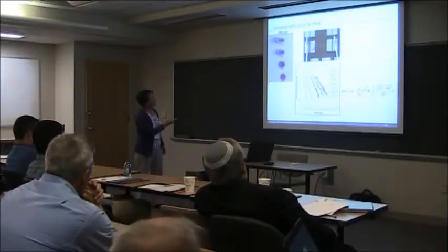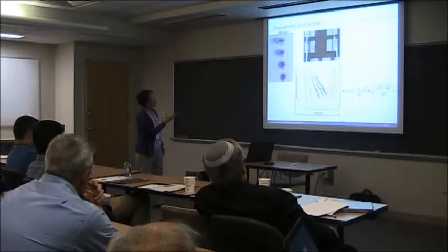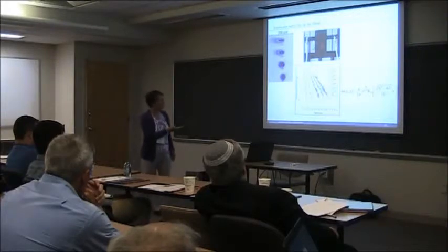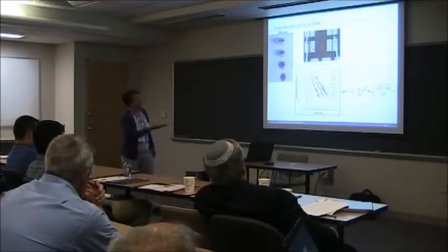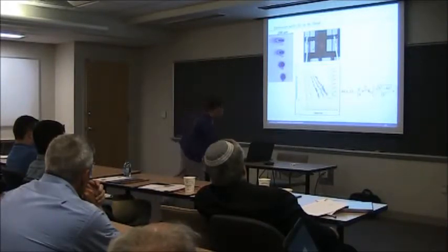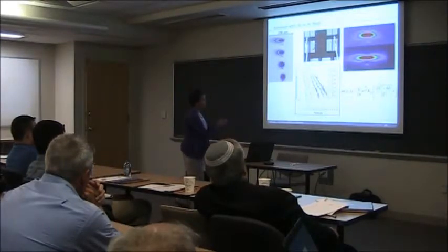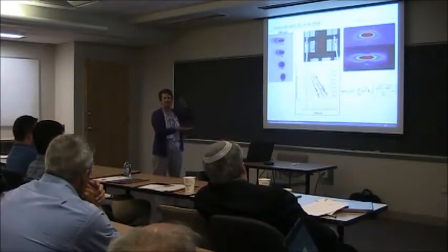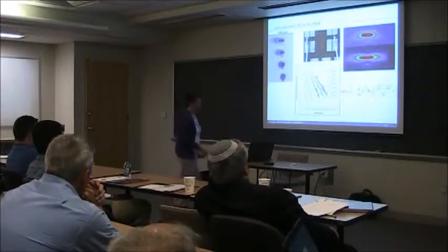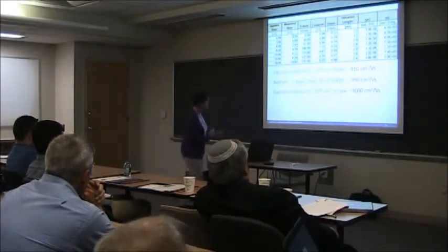Generation point right there, you see the diffusion in the heterostructure, and then as we bias, you see the drift, and you can fit the structures, the math is very well known. You can fit this and extract diffusion lengths. And if you put an AC field on, you can watch it swash around back and forth. You can take nice pictures that way.